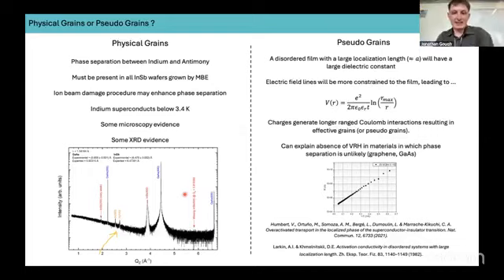Yeah, so obviously we're very limited by transport measurements, because they give you a global picture, essentially the average over the entire property of the system. So you need a very local measurement. And some of my colleagues at University of Paris-Saclay do these low temperature conductive tip AFM measurements, where they essentially scan the surface of the material and they look for evidence of these grains, these high conductivity regions, compared to this background insulating regime. But within our lab, we're essentially limited to transport.